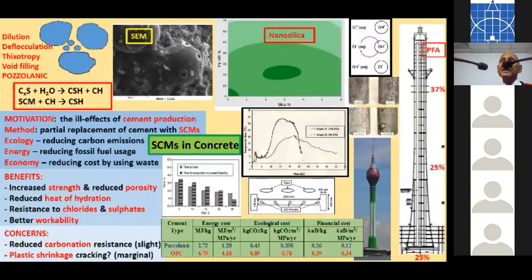But actually we should not be comparing it like that. We should be comparing it not only on the basis of 1 bag of cement or 1 kilogram of cement, we should be comparing it on the basis of what kind of strength can be achieved by that cement and what kind of duration can be experienced by a structure that has that cement. So these are performance-based cost indices. So this is kilogram carbon dioxide per cubic meter per megapascal per year of use. So here we can see that the pozzolanic cement actually is 1/4, not just 1/2, 1/4 of the OPC. Of course, this is exposure or service life in a marine environment.